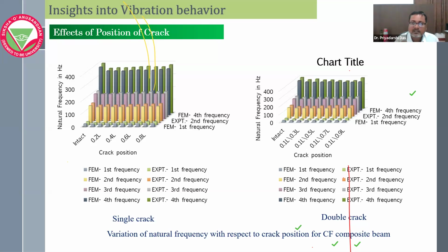For two cracks, keeping that 0.1 L constant because that is the critical, the second crack is varied from 0.3 L to 0.9 L. Now, for that analysis, at what combination of two crack positions will the beam exhibit the greater reduction in the frequencies? So now here you can find that at 0.1 L and 0.3 L, that combination will experience the greater reduction of the frequency.